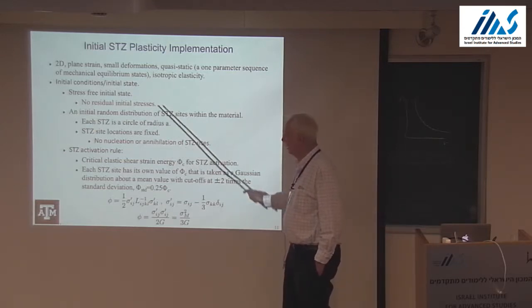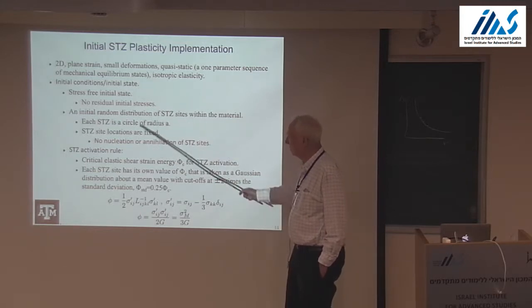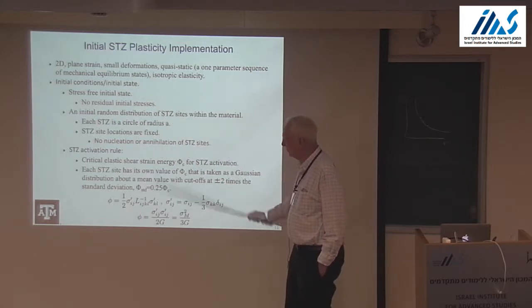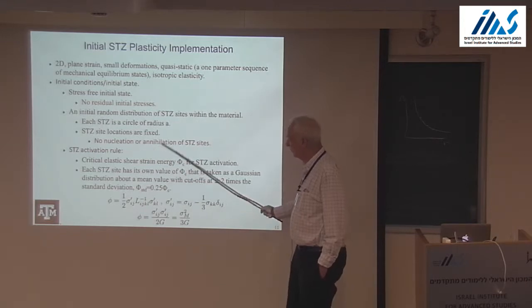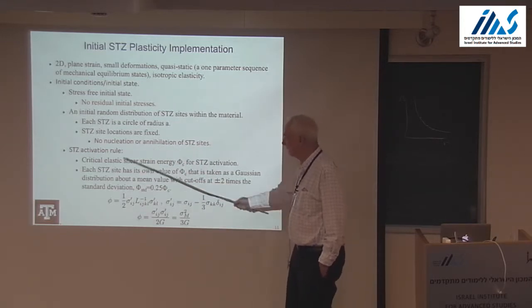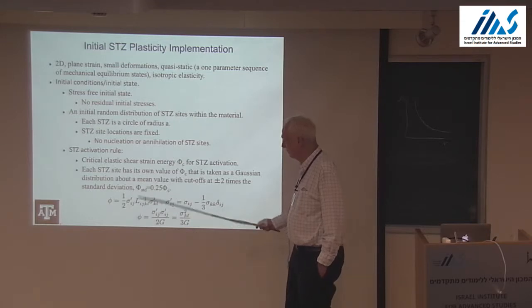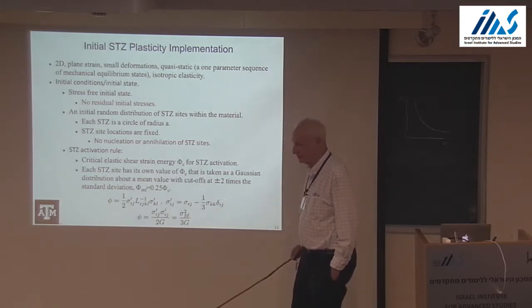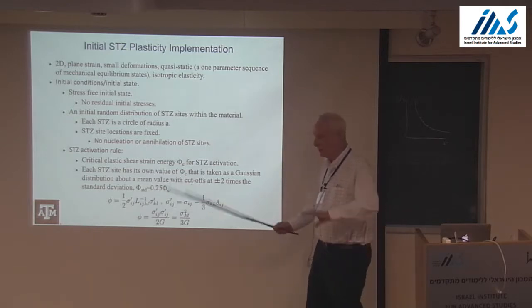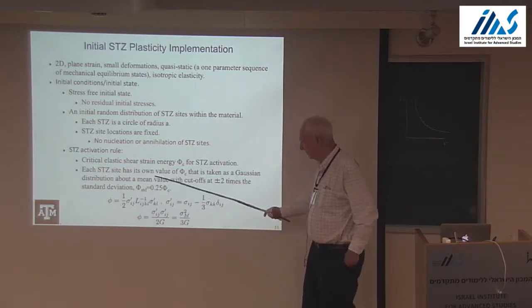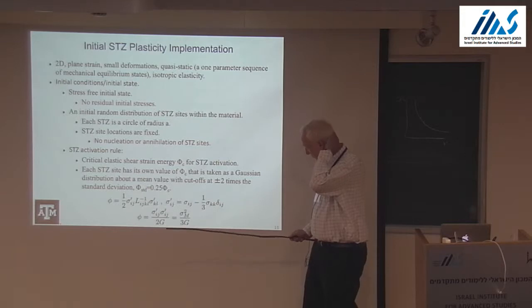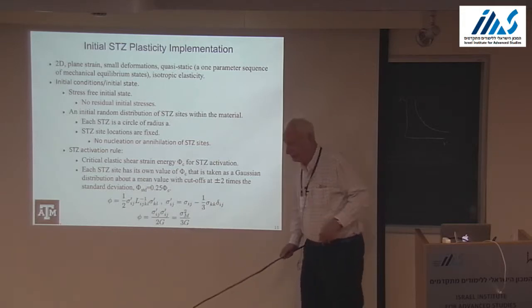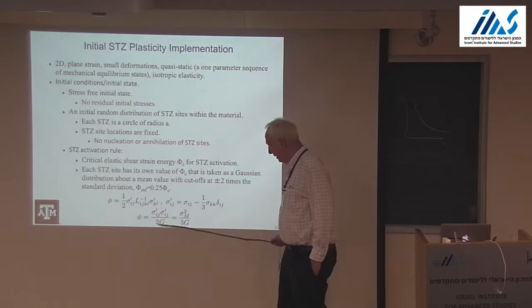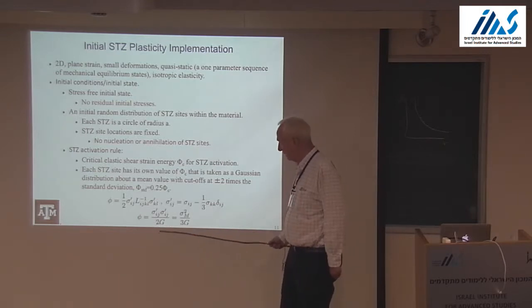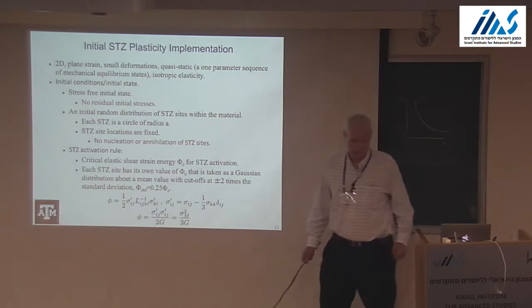An initial random distribution of sites. Each site in 2D is a circle, easiest. With no nucleation or annihilation. We need that. We have an activation rule, and we use an elastic strain energy critical value. We have put in a Gaussian with cutoff, so we don't have very low or very high values. It turns out, and I think a number of people have used a Mises stress type plasticity criterion, it's really the same thing. Once you have isotropic elasticity, it doesn't matter.